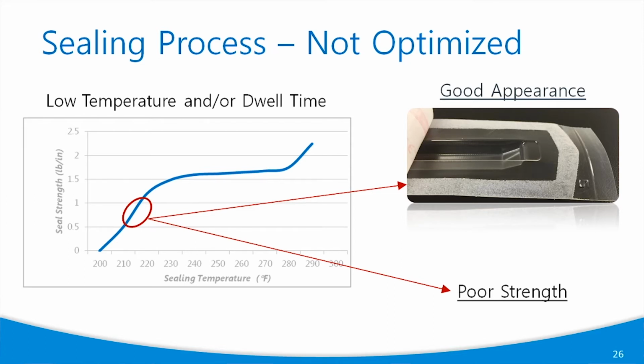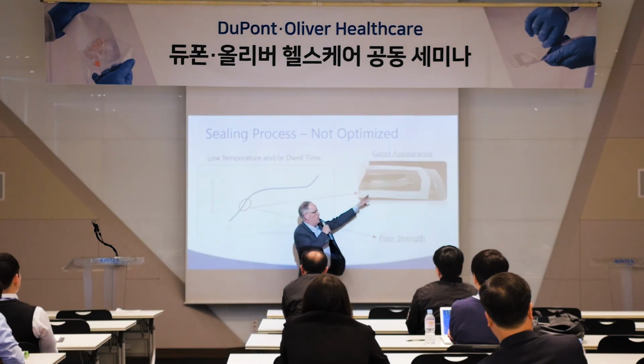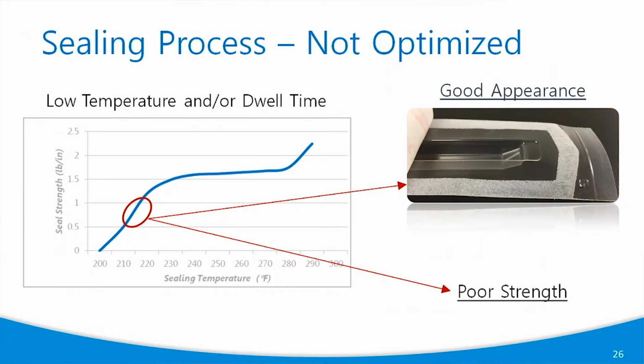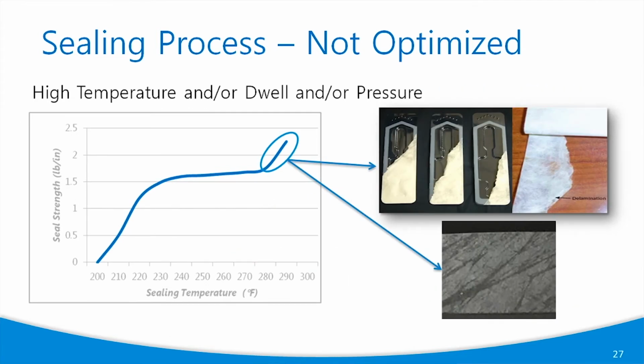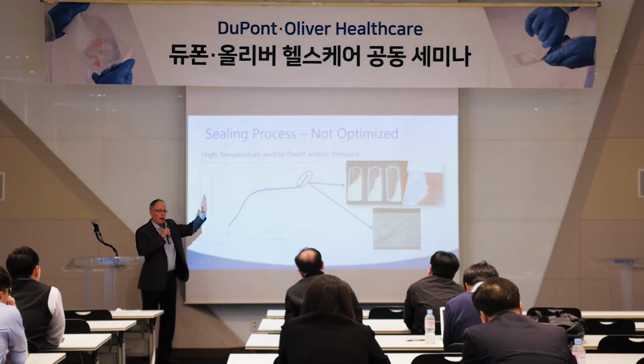So this is another example where you're not optimized, but it's not quite as obvious. Especially if you're using a water-based coating, you can be not optimized, meaning you don't have enough temperature or dwell time, but cosmetically the seal looks great. However, when you start measuring your peel strength values, they're going to be a little bit low, they're not going to be very consistent, you might have a lot of variation, so just be careful about that type of scenario. This is also a very common occurrence that I see with our customers when I'm troubleshooting, and that is to go to the other end of the spectrum and overseal it. So the thought typically is, hey, I want the strongest seal, so I'm going to use the most temperature and the most pressure to try to make a really strong seal, but that's not necessarily a good thing to do.